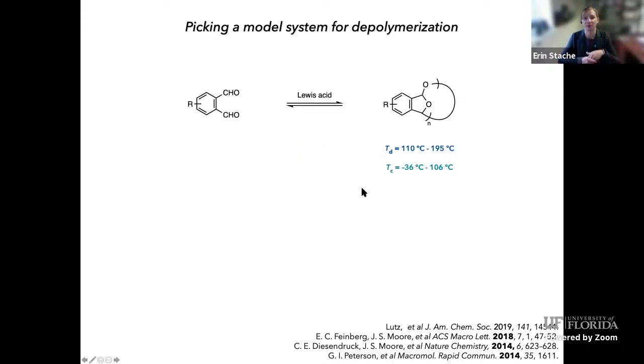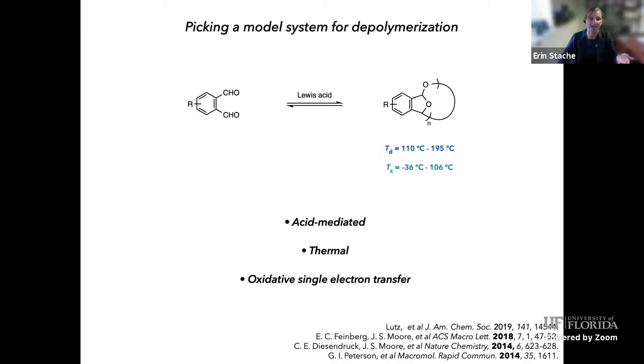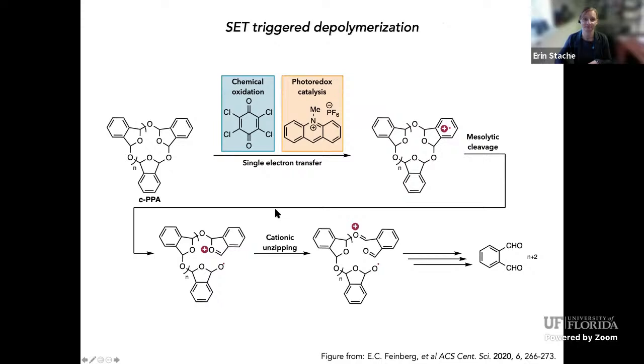To make these polymers, we've been developing a few methods on our own, but also using some of the literature precedents. Usually you just take a Lewis acid and you can make the cyclic poly(phthalaldehyde). Now to depolymerize, a number of different stimuli have been used. It's not stable to acid, so throwing in some strong Lewis acid or Bronsted acid will depolymerize it pretty quickly. You can heat it up above its degradation temperature and it'll depolymerize. You can sonicate it and break the polymer up that way. And most recently, Jeff Moore showed that you could use visible light and do single electron transfer to oxidize the polymer and push it towards depolymerization.